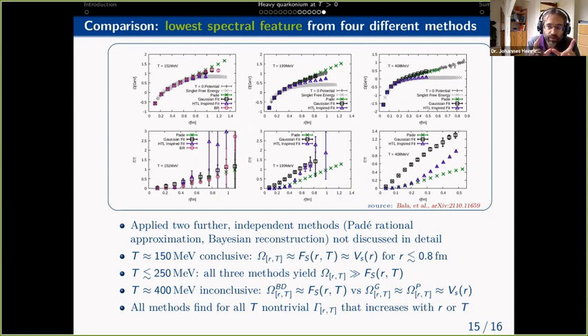So near TC, the screening that you see in the free energy is actually due to the standard string breaking. So the vacuum string breaking, where your heavy quark anti-quark system can dissociate into a heavy-light meson on one side and a daggered heavy-light meson on the other side. That is something that is possible in the operators that you use for computing the free energies, but you can't see it in the operators that you use for computing the potential and the static energy. It's just because of the overlap with different states.